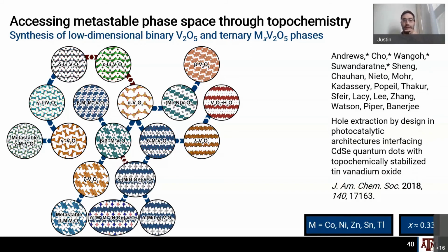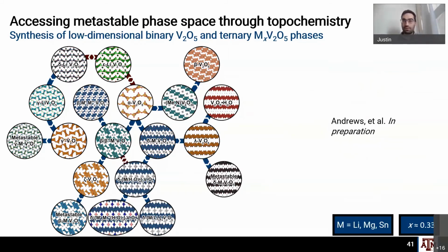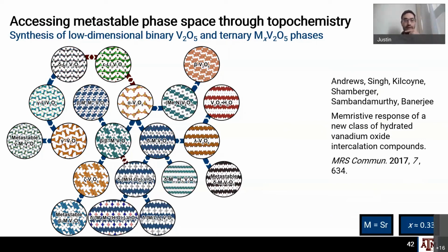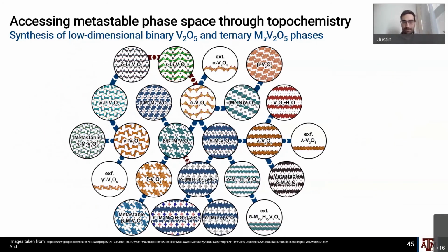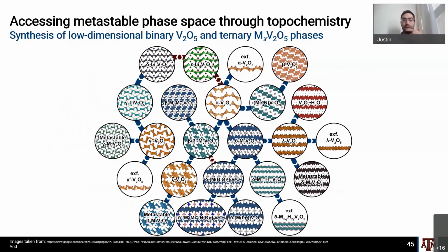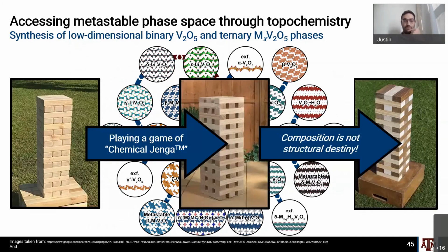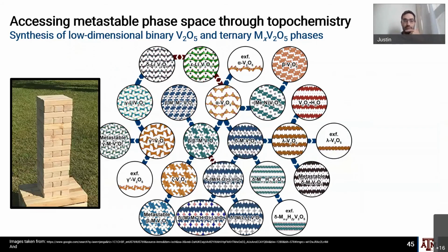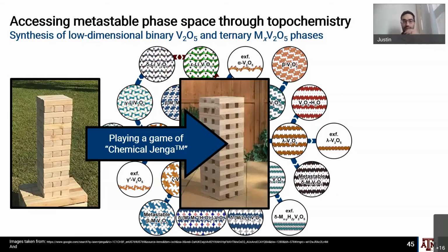We can hydrate this as well. I'm going to go through this relatively quickly, but all this is to show that we have a very expansive phase space that we've been able to develop, where we've got different materials with the same composition but different structure that allow us to look at energy storage at a very fundamental level. I like to joke that what we're doing is playing chemical Jenga. If you've played this game before, we can essentially take V2O5 here in the center and put different ions into its structure to mold the V2O5 sublattice the way that we want, and then pull these out to access metastable structures that we couldn't access directly through just application of pressure and temperature.